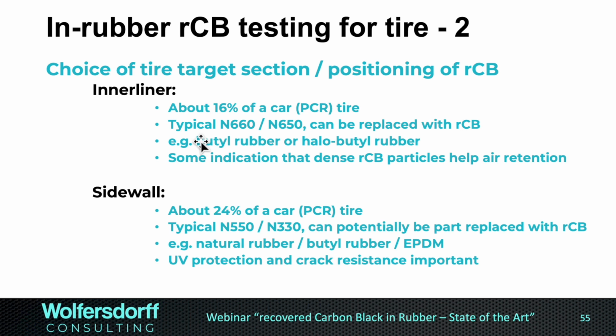So what else? What is left? Of course, the inner liner and sidewall, which are chunky sections of the tire. Inner liner, butyl. We have some indication, which I didn't publish, which came from now Circtec. Peter Tahar did that back then. Some indication that the density of the recovered carbon black particles actually helps in the air retention, and that recovered carbon black could be better in air retention than the N660.